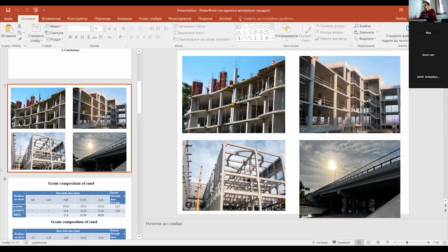Low cycle fatigue. Various studies have shown that changes in the structure of concrete due to the size of the aggregates lead to shifts in the levels of load corresponding to the lower and upper limits of microcrack formation. These studies found that coarse fractions as structural elements of concrete act as stress concentrators, causing stress fields at the matrix-aggregate interface, where microcracks are primarily found.